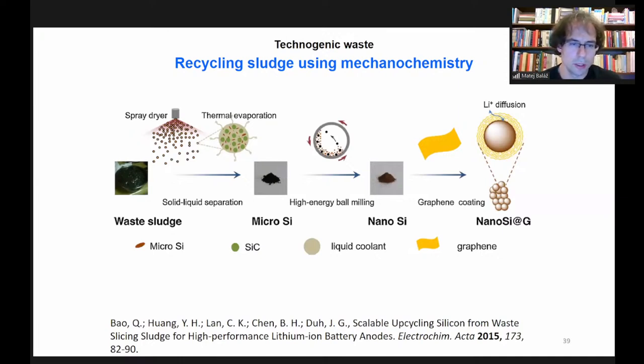Another technogenic waste is sludge. So it's waste where the process when it is formed is performed in liquid phase, and we have something a little bit wet. And in this case, the authors managed to transform it into nanoparticles of silicium, and even coating it with graphene resulted in materials useful for lithium ion batteries. So this is another nice example.